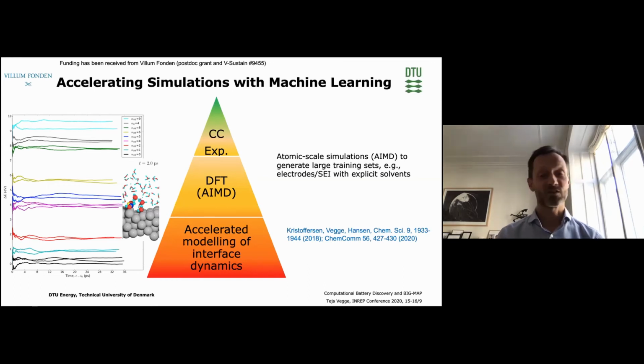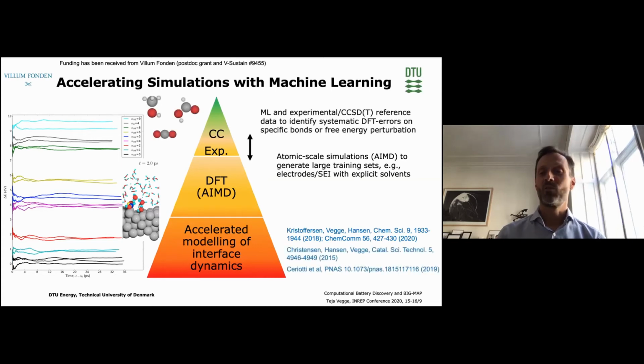That gives us a large training set, but it also encounters another problem, and this is one thing that even though we're using state-of-the-art density functional calculations, we know that there are certain chemical bonds that are not described well, even at this level of theory. So the making and breaking of carbon-oxygen bonds, for instance. But there we can rely on machine learning techniques. This is work done by Rune Christensen and others, where we can automatically identify what is the origin of any intrinsic errors in the calculations.